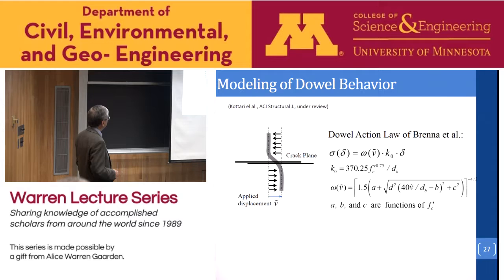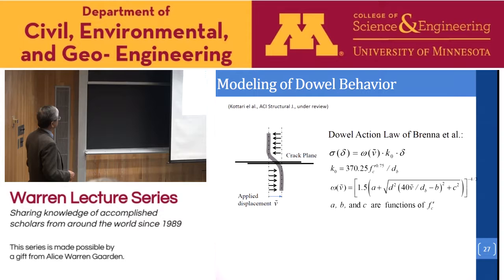So this is a dowel law by Brenna. It's based on monotonically increasing loading. So it's essentially an empirical formula calibrated against the test data. All these parameters here are based on the strength of the concrete. So the model depends on the concrete strength as well as on the bar diameter. We find that this model compared with test data is quite reliable. We implement this dowel in a zero thickness interface law.